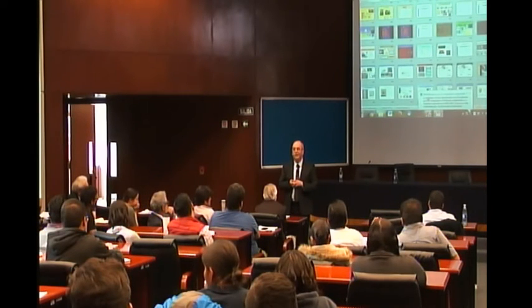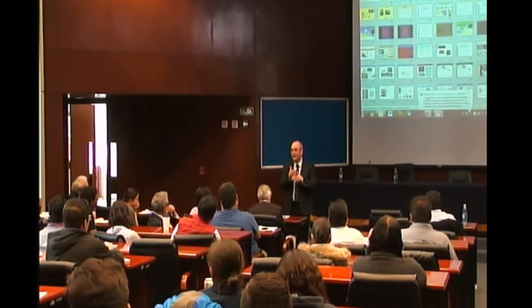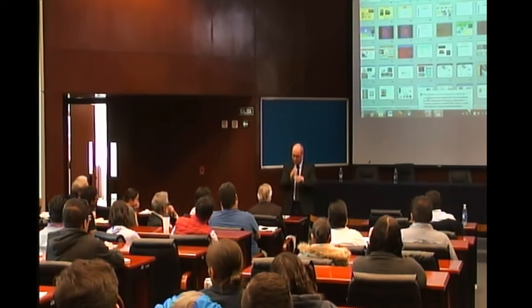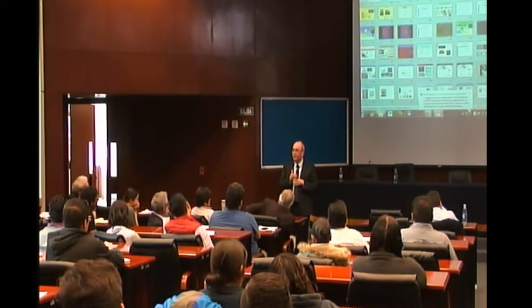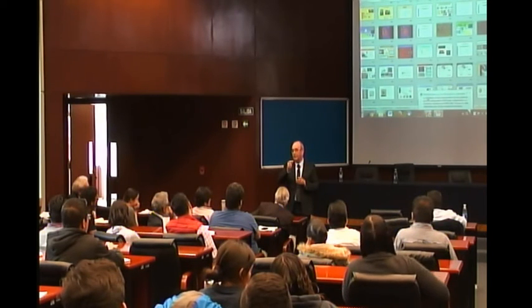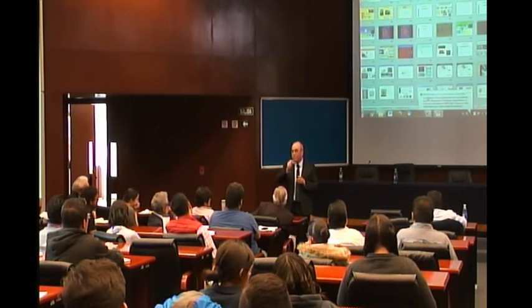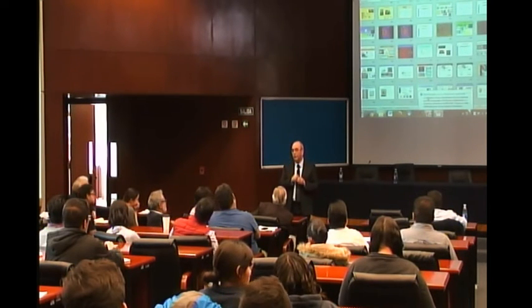Yes, by the dielectric properties. Today, the nanotechnology people are working with crossbar techniques. When you have a crossbar, at the point where you have the cross, you can put your current for heating, but you can also measure the dielectric properties. You have a capacitor, as I told you, and you have a change of the dielectric constant. That means that by measuring the capacity of the point, you can see in which state you are. So you can electrically read your information without using any optical.